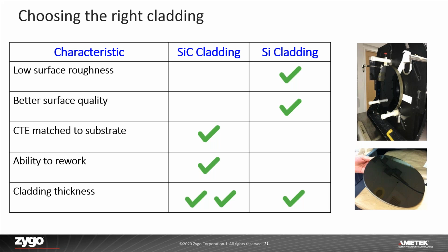As it relates to silicon cladding, you're going to have a lower surface roughness and better surface quality. The silicon cladding introduces, though, a CTE mismatch. It does tend to be thinner, less than 30 microns, so it conforms to the base substrate very well. However, it doesn't leave room for potential rework in the event that you pick up a defect during the manufacturing process, so that is a consideration.